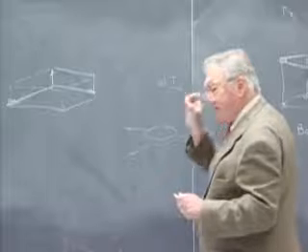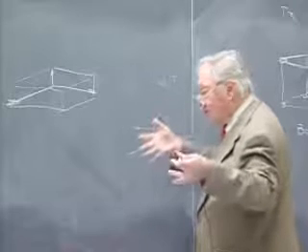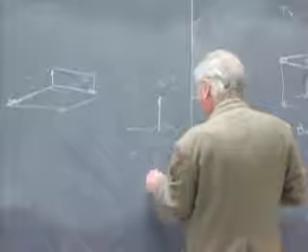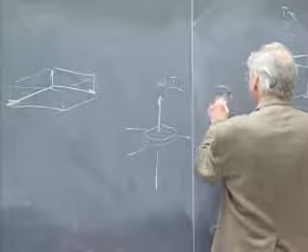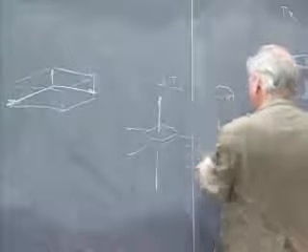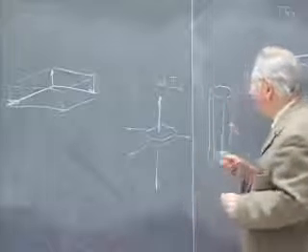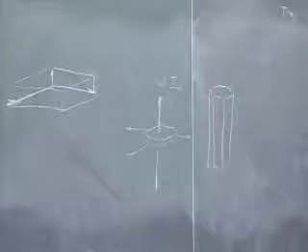Then all of a sudden something happened. And suddenly the rate of growth and the nature of the morphology changed. The crystal took off like a bat in these directions and finally ended up in a needle-like fashion like this. This was an observation that led to the dislocation theory of crystal growth.